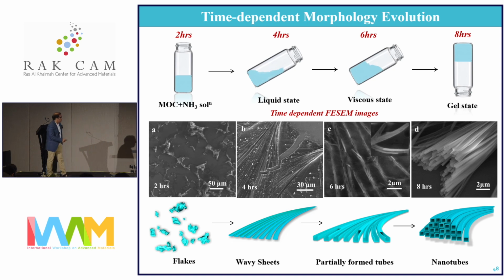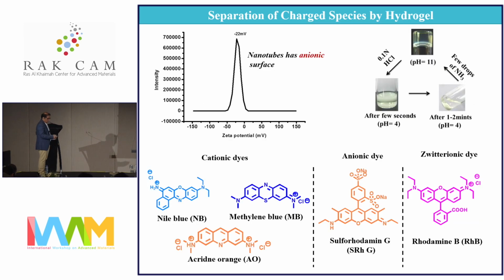So what can we do with this nanotube? When we measure the zeta potential, we find it is negatively charged. Being negatively charged, it can absorb cationic dyes and reject anionic dyes, while partially absorbing zwitterionic dyes. This gel is also pH dependent.